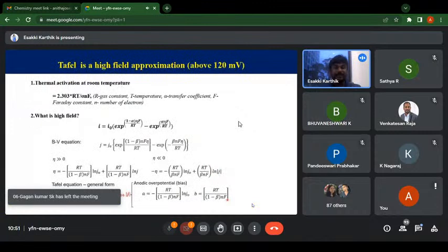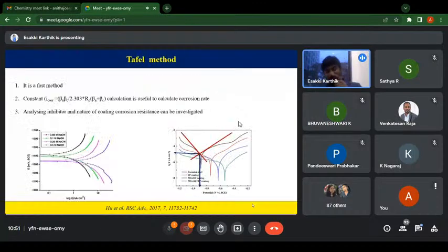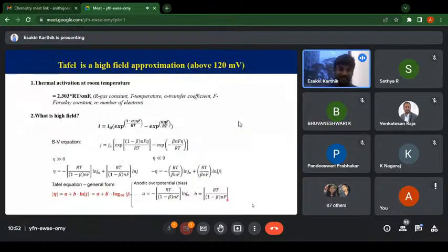Here the question is, I told you we can take the tangent line. Exactly where do we have to take the tangent line, because it is a curvy nature? Whenever you see a curve, it has infinite tangents, because a curve doesn't have a single slope; it has a function of slopes. In general, people will take 120 millivolts from the corrosion potential. That is the Tafel region. Why are we taking 120 millivolts? That region we call the high field region.